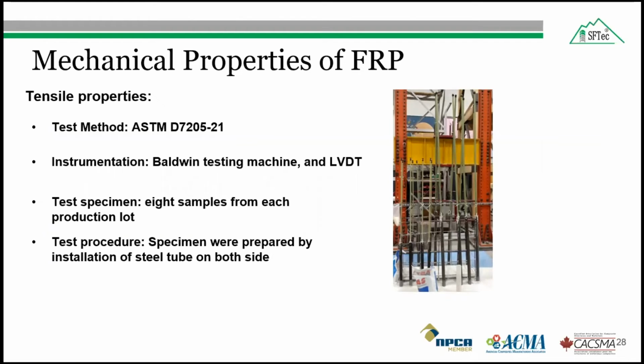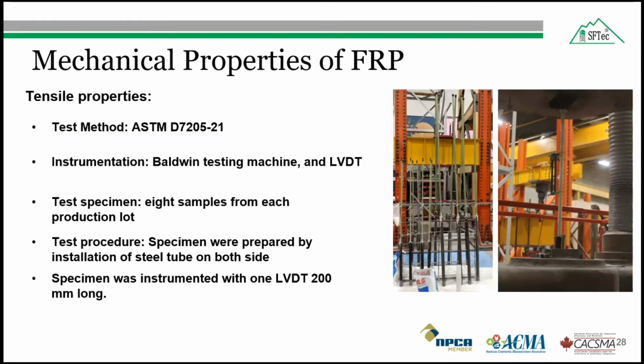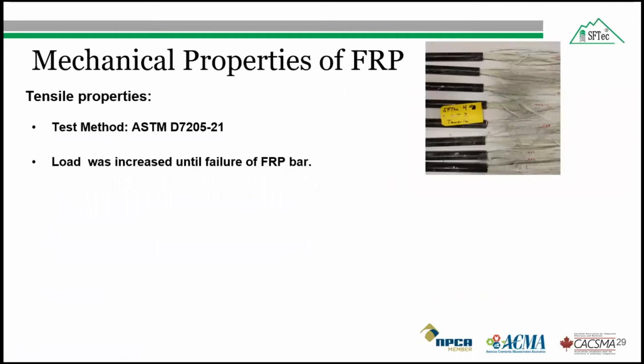In the test procedure, first we have to prepare the sample by installing a steel tube on both sides of the fiber reinforced polymer bar using expansive cement. After the specimen was prepared, we keep it for 3-4 days for curing. Then the specimen was instrumented with 1 LVDT of 200 millimeter length to capture the specimen elongation during the test. The test was carried out using the Baldwin testing machine as shown in this figure. The tensile load was applied until failure occurred, and the applied load and the bar elongation were electronically recorded using a data acquisition system. So after my test, I got the data from the acquisition system.